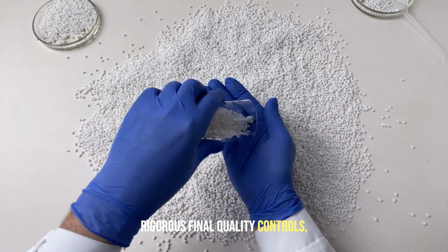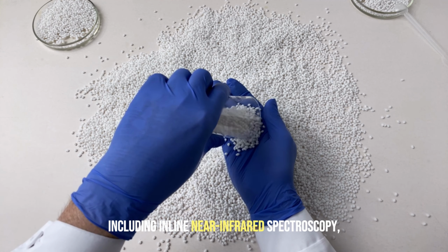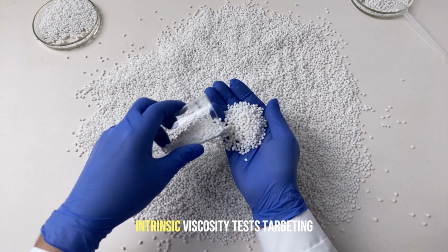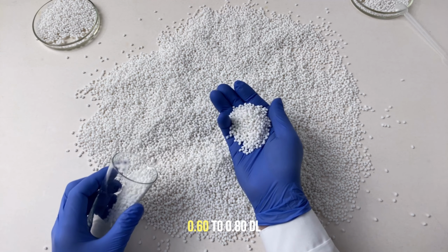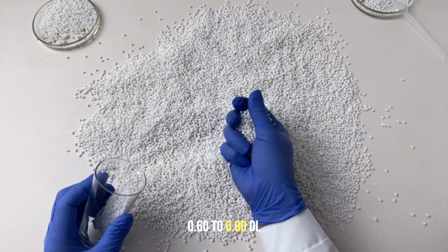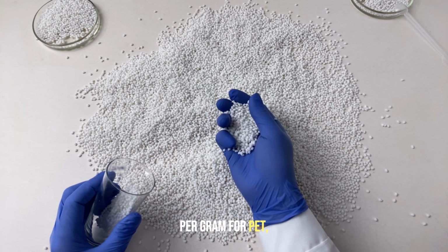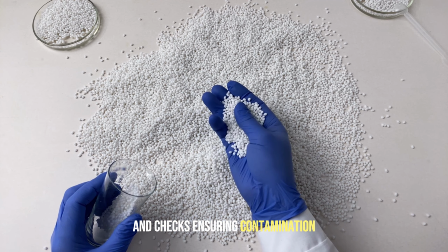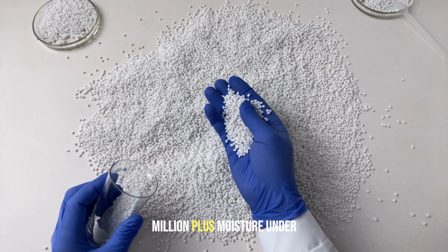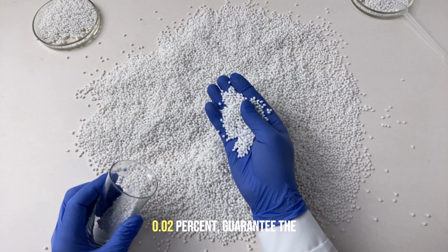Rigorous final quality controls, including inline near-infrared spectroscopy, intrinsic viscosity tests targeting 0.60 to 0.80 deciliters per gram for PET, and checks ensuring contamination below 50 parts per million plus moisture under 0.02%.